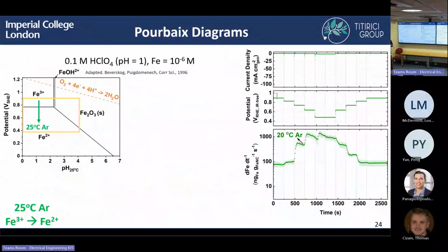So this is quite confusing, but I'll keep going and hopefully it'll make more sense once we talk about the Pourbaix diagrams. So going back to A-level chemistry, hopefully everyone remembers Pourbaix diagrams. Again, this is just the initial GDE ICP-MS measurement in argon. So as we step down in potential, we see this very clear increase in the iron dissolution.